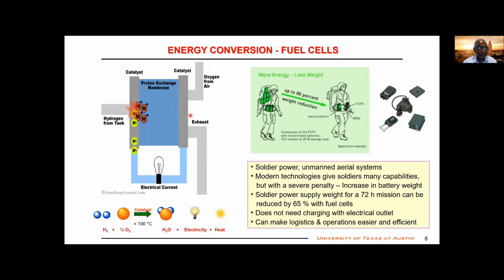And as long as you supply hydrogen and air, you will be continuously getting energy, unlike the batteries. Batteries, when the charge is over, you have to find an outlet. Here, as long as you have the hydrogen tank somewhere, you can get energy. You do not have to use just hydrogen gas. This could, in principle, work with a liquid fuel like methanol or ethanol, but fuel cells also have too many challenges. For doing this reaction, you have an expensive catalyst like platinum. That's very expensive. Also, hydrogen fuel cell is the easiest, less problematic. If you use methanol or ethanol, you have more problems. So in fact, fuel cells have more problems from a cost point of view or other considerations than the batteries.